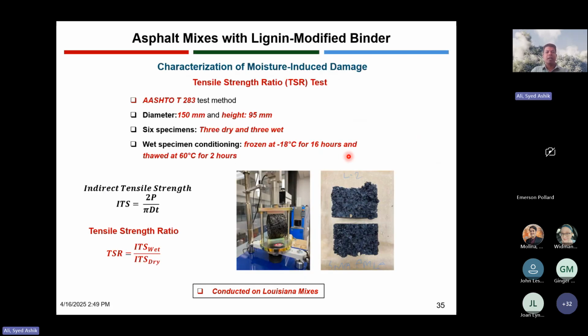We also evaluated the moisture-induced damage characteristic of the asphalt mix using tensile strength ratio, or TSR testing. TSR was done using AASHTO T283. We prepared a 150 millimeter diameter sample with a height of 95 millimeter. We used 3 samples for dry conditioning and 3 for wet conditioning. The wet conditioning was done using 1 freezing and 1 thawing cycle. After determining the indirect tensile strength of the asphalt mix, we compared the strength at the wet condition over the dry condition. And this was done only on the Louisiana asphalt mix.